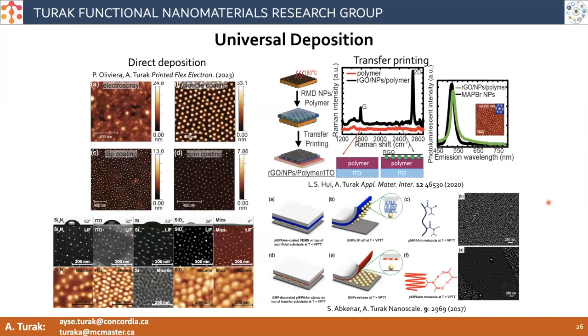And the nice thing is that, in addition to being kind of a universal technique for materials, it's also universally depositable. It's not only agnostic to all these different techniques, but also to the surface. It's possible to deposit them, though again, not exactly the same. They don't form the same arrays on different surfaces, because they affect the surface tension, the surface energy of the surface. But whether you have a high energy surface or a low energy surface, you still can get particles forming on the surface. So that makes it really powerful because you don't have to care about what's happening on your substrate. You can form them independently and then deposit them on the surface. So this is a huge advantage over quantum dots that are grown epitaxially, because you're limited by what you can produce on a given substrate.